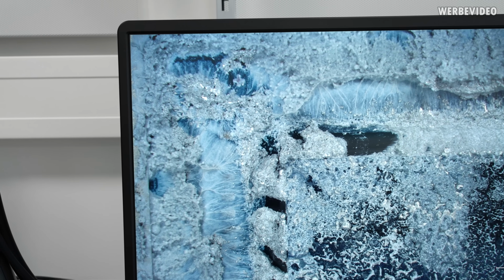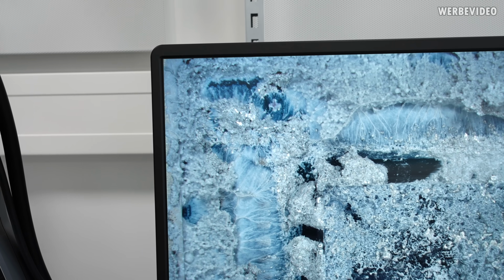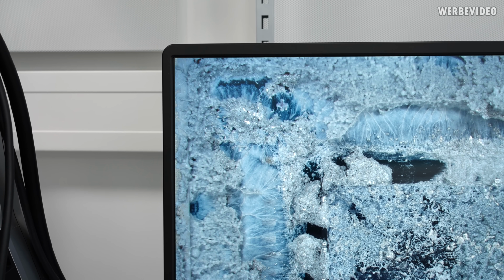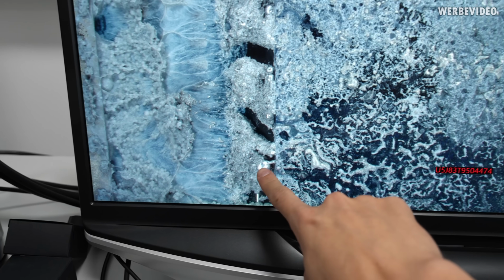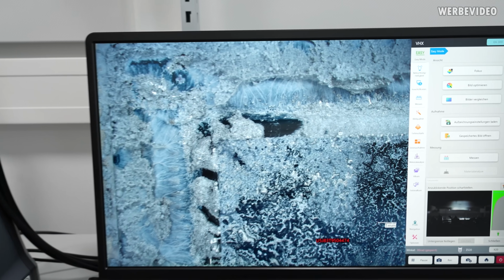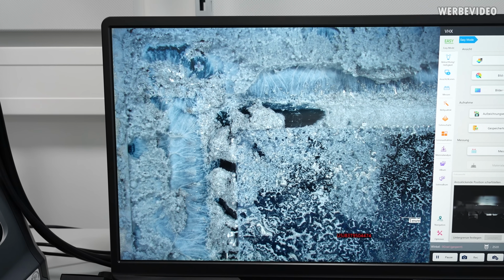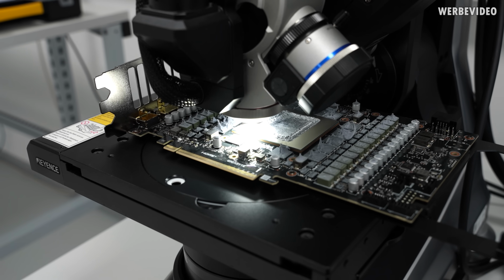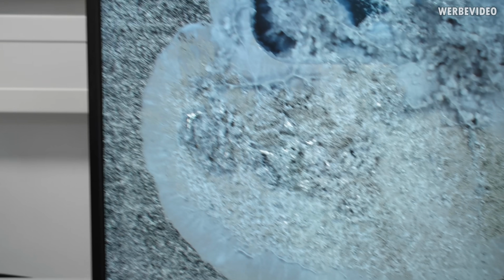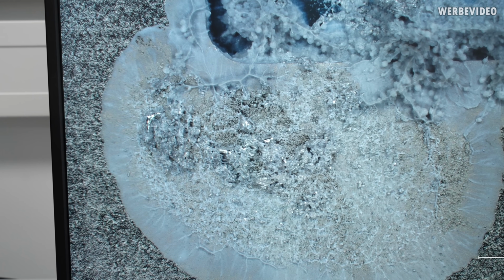And looking under this 20 times magnification, we can easily spot some of the shiny areas that highlight the gallium-indium alloy, so that's the liquid metal. In this area we can see a lot of this shiny liquid metal. Also here there's a droplet, a bigger one down there, here, and also in that area you can clearly see it. So it's definitely a hybrid paste, like a mix between a normal thermal paste and the gallium-indium liquid metal. And now the area on the bottom left, also here we can clearly see traces of the liquid metal that was in this case pushed out, I think, a little bit further than what was originally intended.